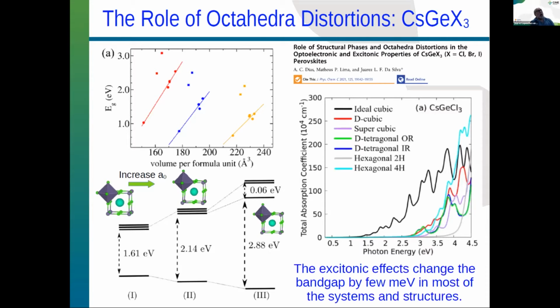And here I show the total absorption coefficient, where you can see that the ideal structure, because it has a smaller band gap, absorbs at quite a small cutoff photon energy. After that you have a displacement because of the octahedral distortion, and for the last one you have the hexagonal structures. As Anna Flávia mentioned at the beginning of her talk, the structures start to form in the hexagonal phase, and then they go to the cubic phase, which has quite a nice band gap for photovoltaic applications.